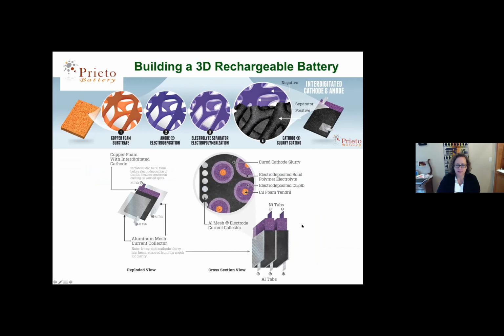Okay, so as I mentioned, we use aluminum mesh as our current collector, and this is a better image of what this looks like. The mesh actually does cover the whole surface area in this arrow here of the cathode slurry, and we dry the cathode slurry around the aluminum so that we have lower impedance on that side. And then to build capacity, we stack layers of this 3D battery. So the thickness of each layer is set by the thickness of the foam that we buy. And then we calendar that whole layer a bit to densify the structure and to densify some of the cathode slurry. And then we can stack these again to build higher capacity cells.